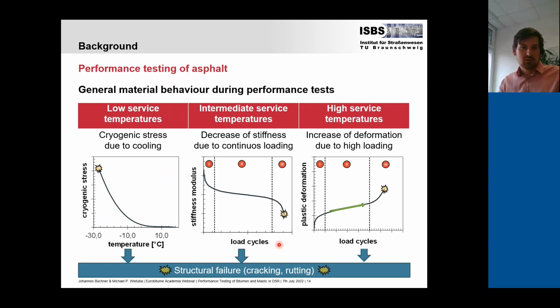Generally, during the performance testing of asphalt, we are looking at the behavior of the material at low temperatures. We basically look at the stresses which build up due to cooling and the shrinkage which is hindered. So here I demonstrate the 3 different material behaviors in the 3 different temperature ranges. At low temperatures, we see the development of cryogenic stresses in the pavement with decreasing temperature, leading to a failure of the specimen, which is here a crack.